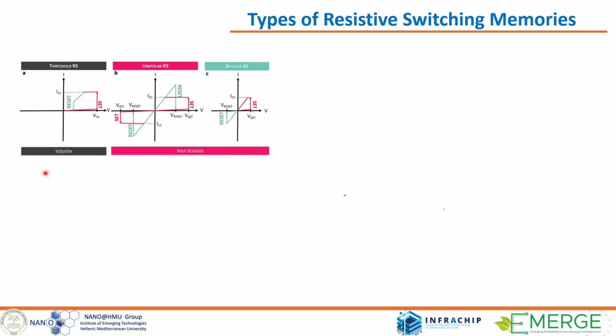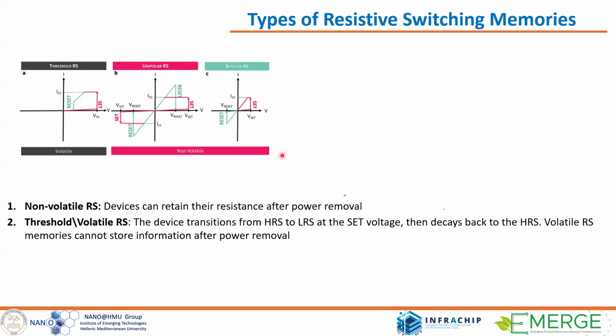And also there are devices that we call volatile memristors. If you see the curve here, if you exceed the threshold, what we call a set voltage, the device jumps to a low resistance state, but then when the bias is decreasing, at some point the system will relax spontaneously to the high resistance state. So this device does not have a long-term memory, however, it can be used to emulate the firing process of some models of neurons, and gives us the second element for neuromorphic systems. The first is the synapses, and the second are neurons, in order to implement a crossbar array and a whole system. Okay.